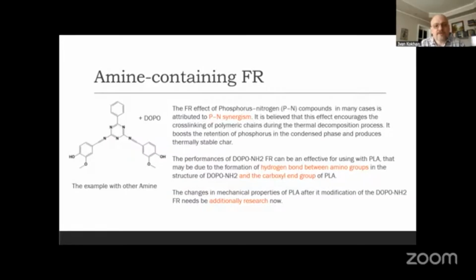Amine-containing FR. The FR effect of phosphorus-nitrogen, PN, compounds in many cases is attributed to PN synergism. It is believed that this effect encourages the cross-linking of polymeric chains during the thermal decomposition process. It boosts the retention of phosphorus in the condensed phase and produces thermally stable char. The performance of DOPO-NH2 FR can be effective for use with PLA, which may be due to the formation of a hydrogen bond between amino groups in the structure of DOPO-NH2 and the carboxyl end group of PLA. The changes in mechanical properties of PLA after its modification with the DOPO-NH2 FR need to be additionally researched now.